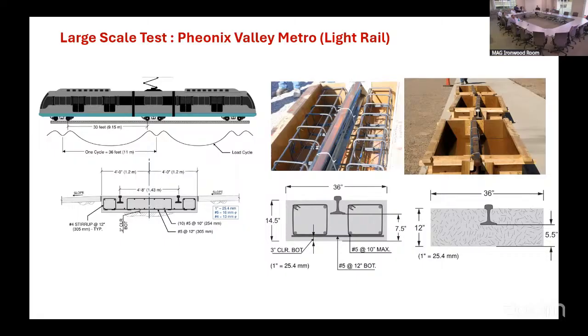If we go to the polymeric fibers, and that's what we proved in the second phase of the project, that meant that we just didn't have to worry anything about the potential corrosion of the rebar and the maintenance. That's a problem that we have. So we made these samples 3 feet wide, about a foot deep, and then we tested it in our lab. Can we go to the next slide?